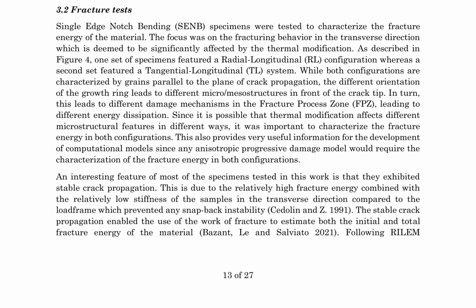Most specimens exhibited stable crack propagation due to their high fracture energy and low stiffness in the transverse direction, preventing snapback instability. This allowed for the estimation of both initial and total fracture energy using the work of fracture method, Bažant, Le and Salviato 2021. The findings from this research contribute to the development of computational models, especially those incorporating anisotropic progressive damage models that require fracture energy characterization in both configurations.